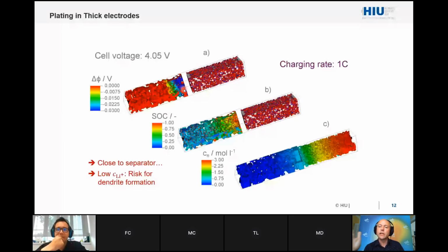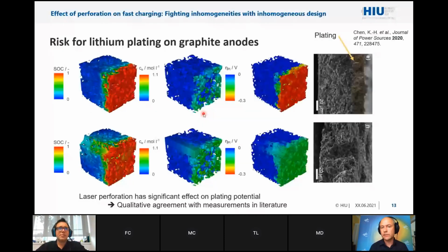So here the inhomogeneity, which is causing plating, is due to the operation under a situation where you wanted to have a high energy density electrode, but you couldn't do it since the power density is not available due to transport limitations. Of course, you can do something, and this is what we did afterwards, namely we're doing the design simulation. So you will see you have inhomogeneities, and now you start to fight inhomogeneities with inhomogeneous design, which is one solution. Here are experiments from Chen. Again, thick electrodes with laser holes drilled into the electrode.